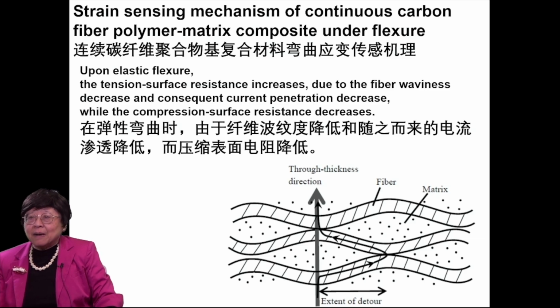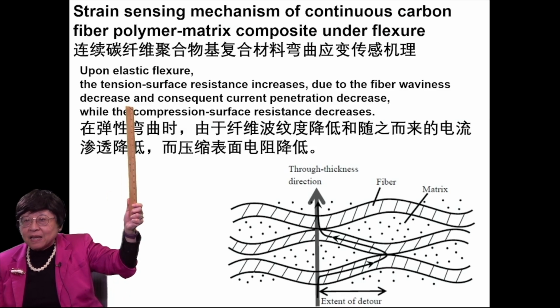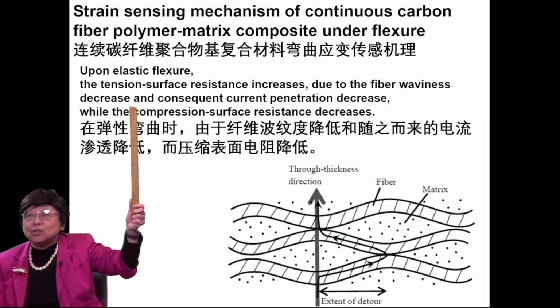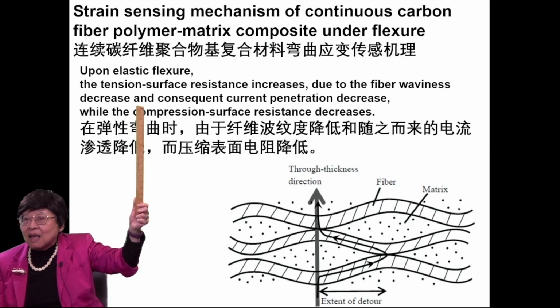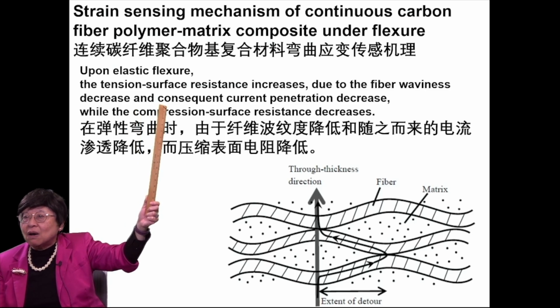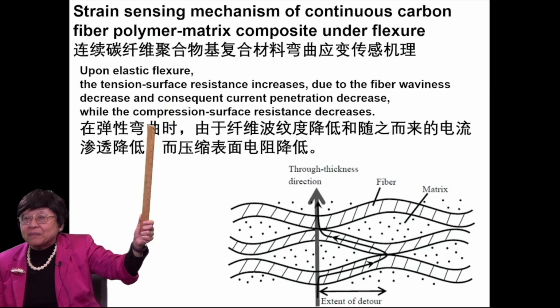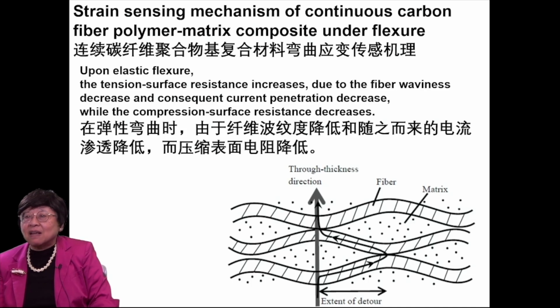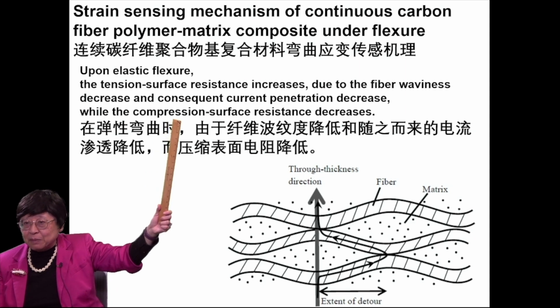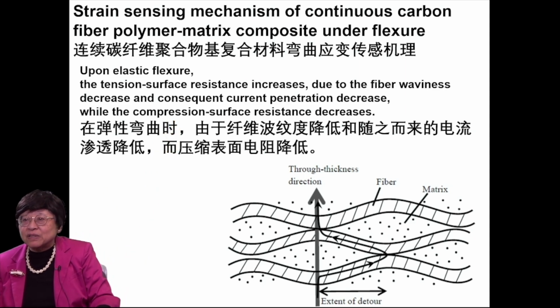This has to do with the fact that upon flexure, the tension surface resistance increases due to the fiber waviness decreasing, and the consequent current penetration also decreasing. And when the current penetration decreases, then the surface resistance would increase. And for the compression side, it's just the opposite, because the compression surface would have the fiber waviness increase, and so more current penetration, and so lower surface resistance at the compression side.